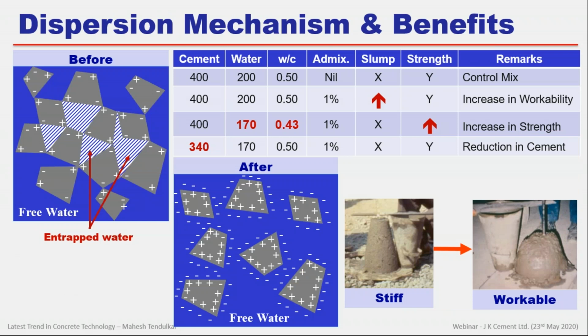This chemical admixture, there is no magic. It is only giving a negative charge on the cement particles, so they repel each other, and the entrapped water is freed, so slump is increased. I am going to share this presentation slide at the end. I will ask the organizer to share these slides, because I have arbitrarily given one example of how it works: mix 400 cement, 200 water, simply, so that we can understand a 0.5 water cement ratio.